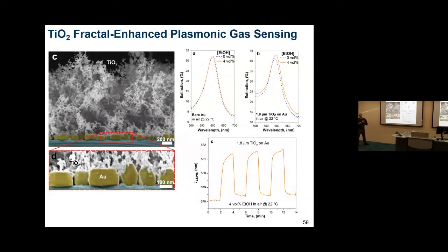So we came up with the idea, can we actually trap this gas molecule in proximity of the field? What we did, we deposit the gold nano island with the method I showed you before, and then we deposit fractal particles on top of it by the same aerosol deposition approach. And what you see is a dramatic change.